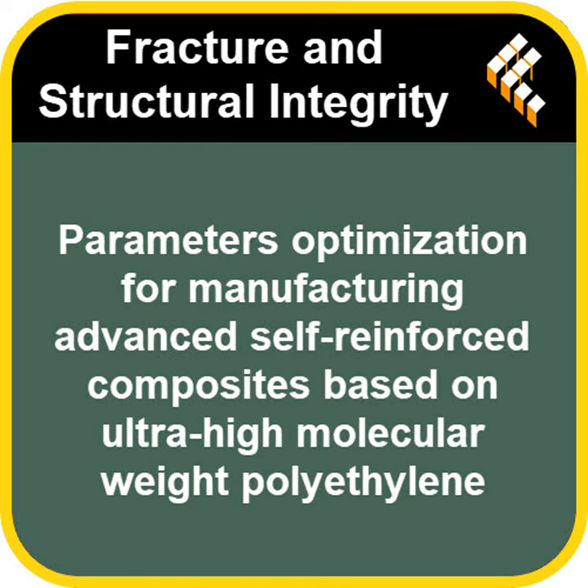What were the numbers like? At the low end, 145 Celsius, it was about 7.8 MPa. It climbed quite nicely to a peak of 11.1 MPa, around 165 and 170 Celsius. Okay, so hotter means stickier up to a point.